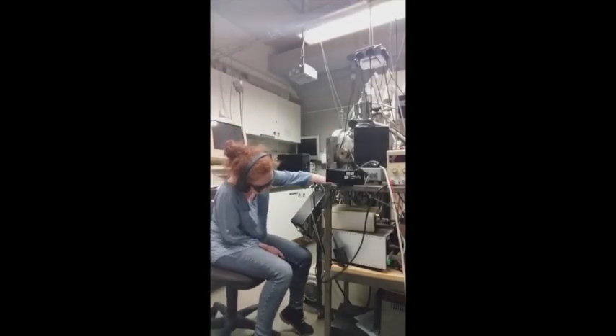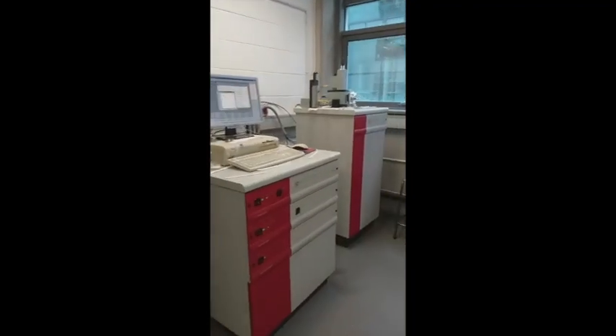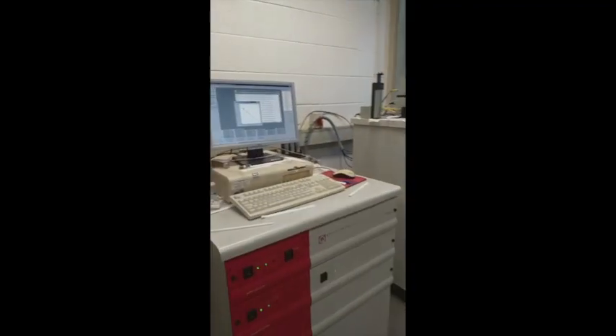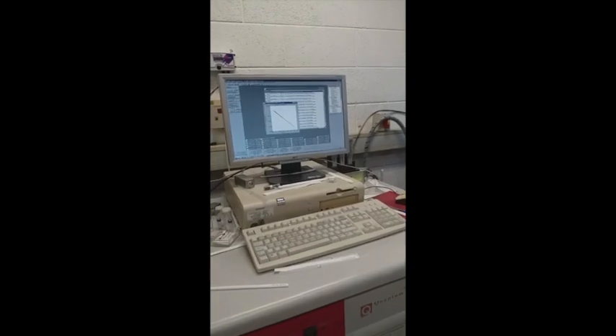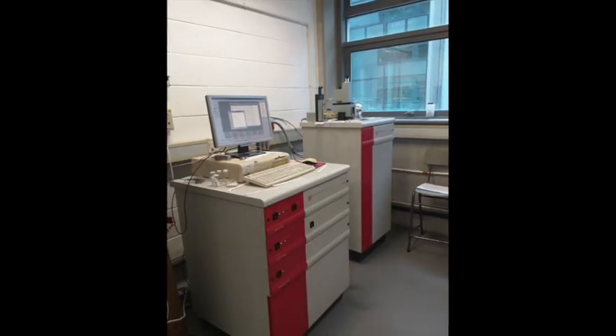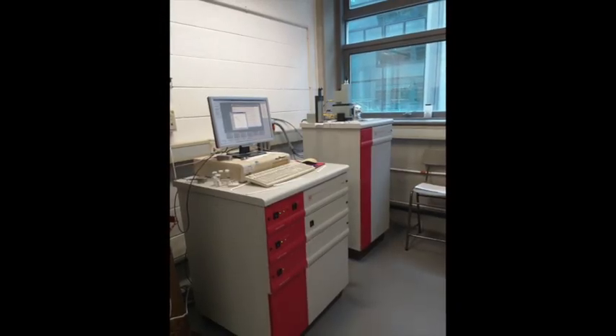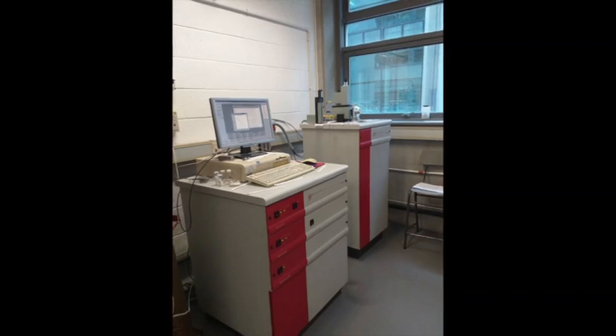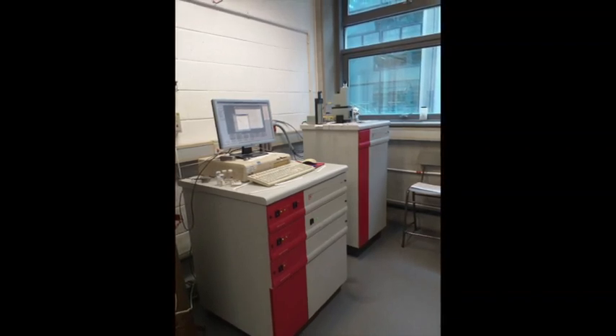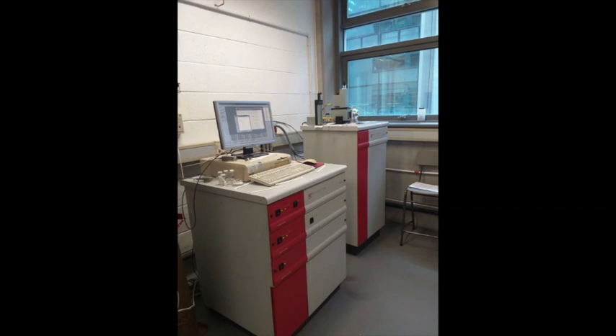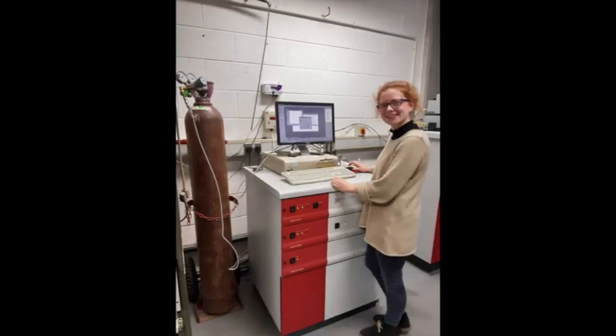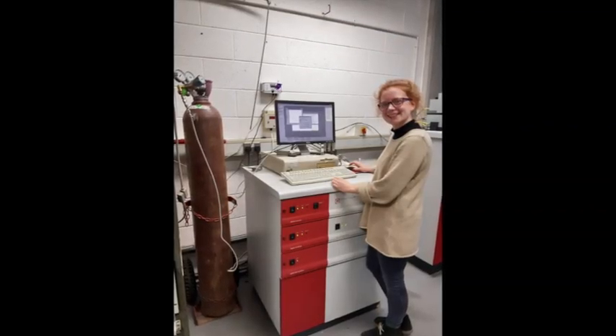After preparing our samples, we need to magnetically characterize them, and the SNIAMS is the home of our very own SQUID magnetometer. So SQUID is a strange name, but it stands for Superconducting Quantum Interference Device, and it allows us to apply a magnetic field to a sample and measure the resulting magnetic moment. We can scan fields of up to 5 Tesla. We can also vary the temperature from 4 Kelvin up to about 400 Kelvin.